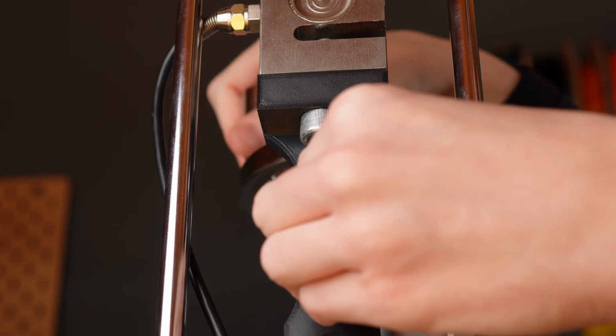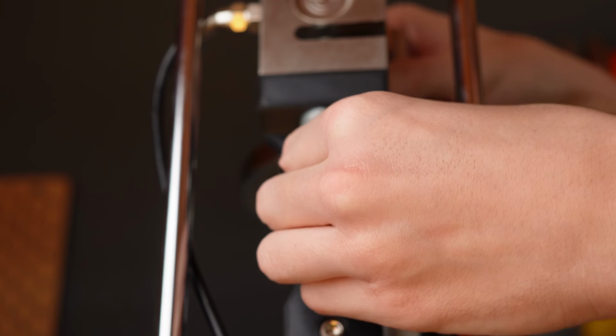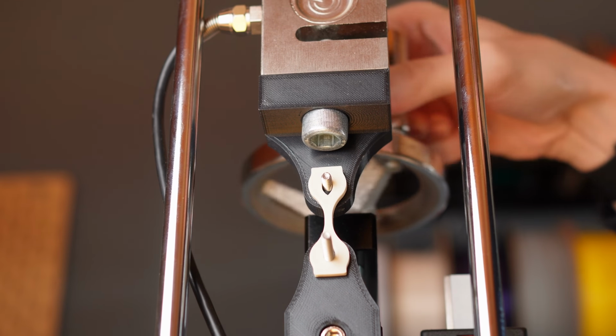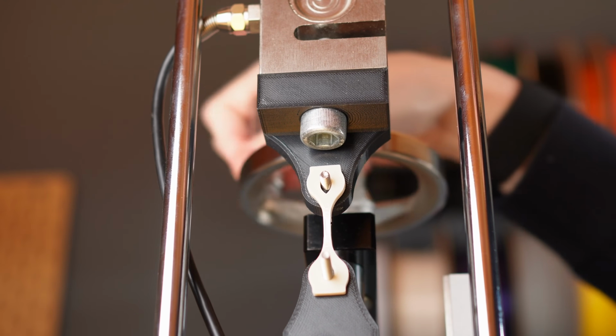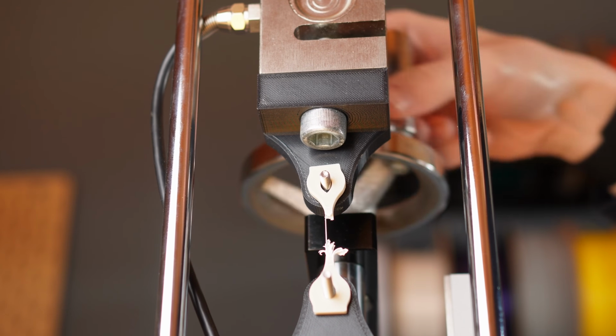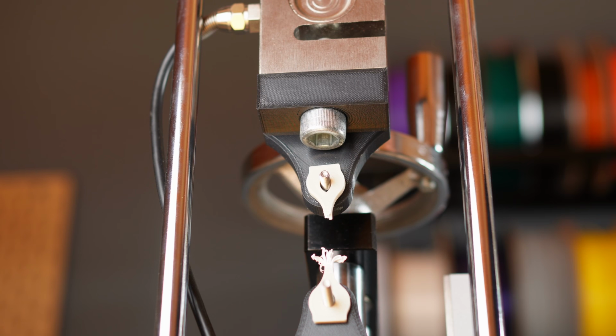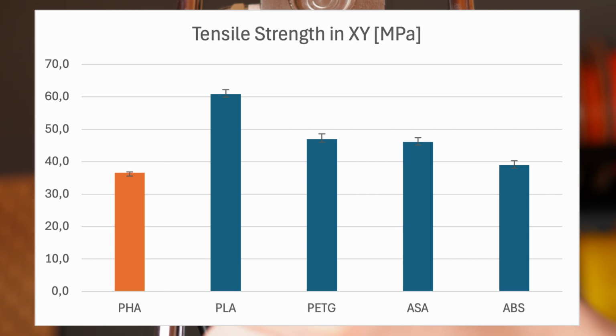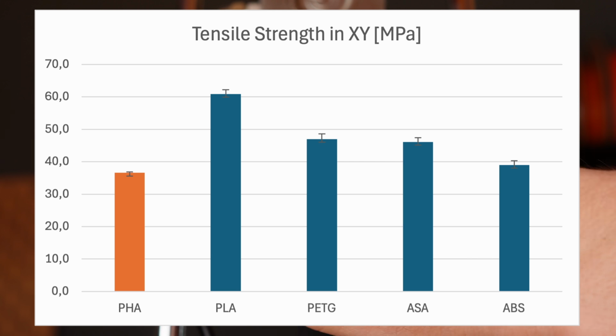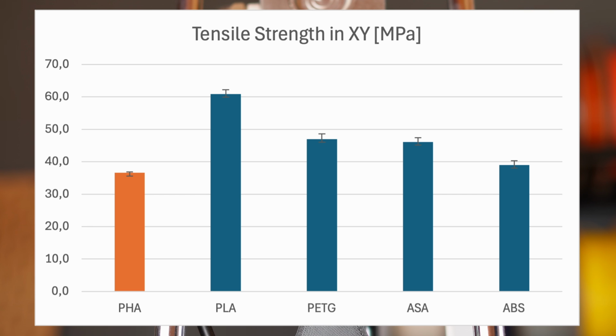I then pulled them apart with my DIY tensile testing machine, measured the force with the load cell and put all the measurements in an Excel spreadsheet. The tensile strength in megapascals, which is tensile force per area, is then automatically calculated. Here you can see the results of PHA in XY direction compared to other common materials I tested before.